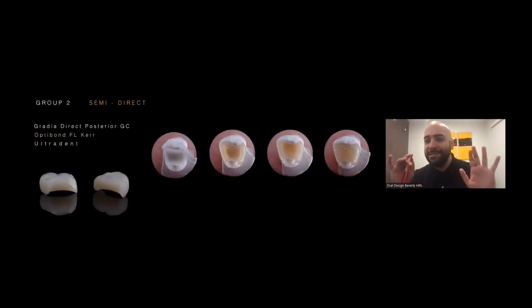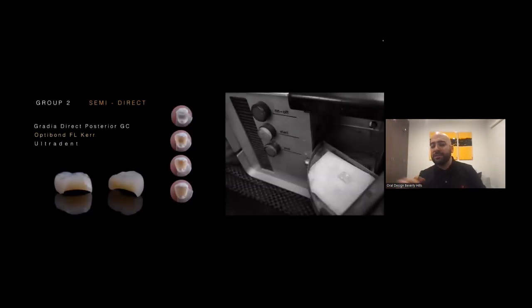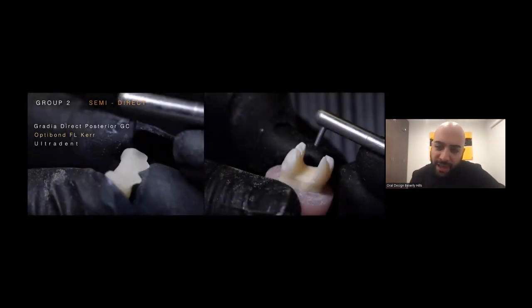Then you pretend as if you're doing a large direct restoration. This separation with the Teflon and the path of draw that you've created allows you to pull out this little piece that you have created in the semi-direct restoration. Then what makes this method very special is that you can simply put that piece in a little oven at 100 degrees Celsius, and that makes this piece do all the shrinkage it can.